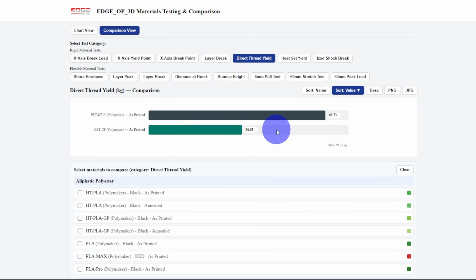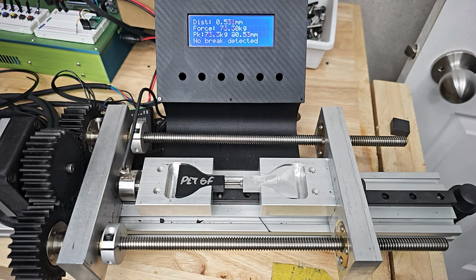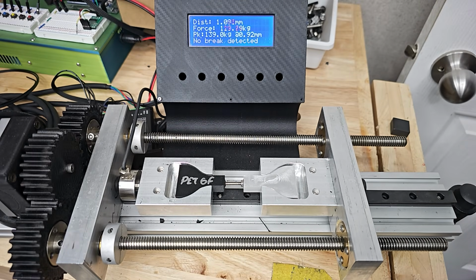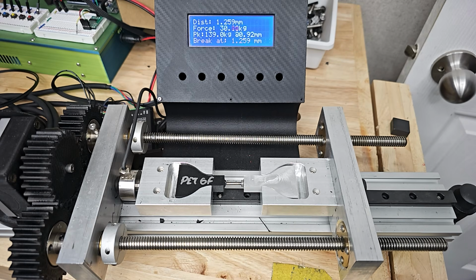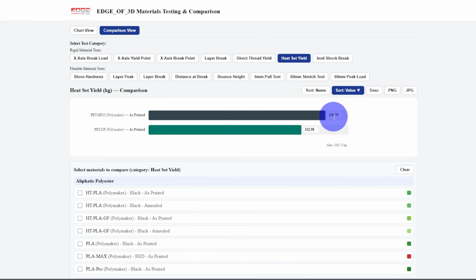69.73 kilograms. That is a very respectable number for a 3mm screw screwed in 4mm into this plastic. You can see the glass fiber compared to the carbon fiber, close to double. Heat set yield. They get a little closer here, but same thing. It's a 4mm deep, 3mm heat set that's used a heat gun to insert it into the part and then pull it back out. 130 kilograms of force. Again, a very respectable number.